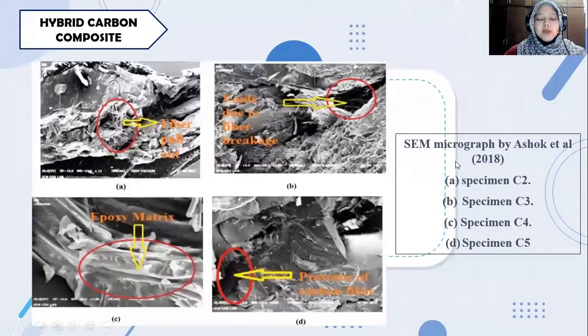Next, on the hybrid carbon composite. This picture is an SEM micrograph by Ashok et al. in 2018. On specimen C2, we have fiber pullout, and on specimen C3, we have voids due to fiber breakage. This may be caused by unsuitable fiber connections, and fibers may break out of the matrix. On specimens C4 and C5, we have the presence of epoxy matrix and carbon fiber. It is concluded that the presence of carbon fiber enhances the mechanical characteristics, and failure of the matrix causes fiber breaking.